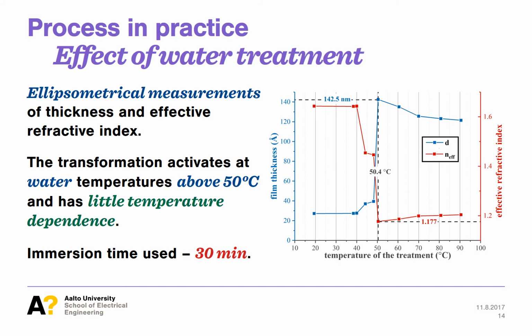A little more details about the grass-like alumina formation. The graph presents results of ellipsometrical measurements performed on grass-like alumina formed at different water temperatures. Ellipsometry is an optical method to measure effective refractive index of a film and a corresponding thickness. We used single wavelength, or laser, ellipsometry.